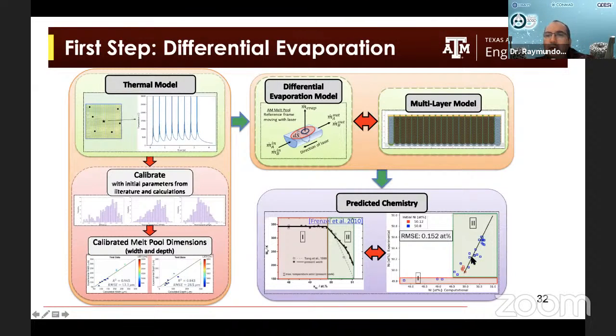And then we compare with the results of the model, okay? And I must confess here that we didn't do any calibration of the differential evaporation model. The only calibration step that we did was of the thermal model, but once it was calibrated, everything else was a prediction from first principles. And we found extremely good agreement. It turns out that the error in our prediction is 0.15 atomic percent, which is several times less than the uncertainty that you get when you do measurements of chemistry in WDS or EDS. Okay, so this is just one step in the process.